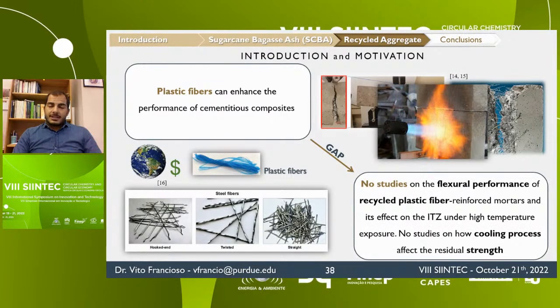Several studies have demonstrated that polypropylene fibers can prevent spalling failure of concrete under compressive loads caused by internal stresses when they are subjected to elevated temperature. However, the influence of elevated temperature on the flexural performance of recycled plastic fiber reinforced mortars and its effect on the interfacial transition zone between the matrix and the recycled fibers has not been deeply investigated. Moreover, no studies were found on the possible effects of the cooling processes on the residual strength of these eco-mortars.